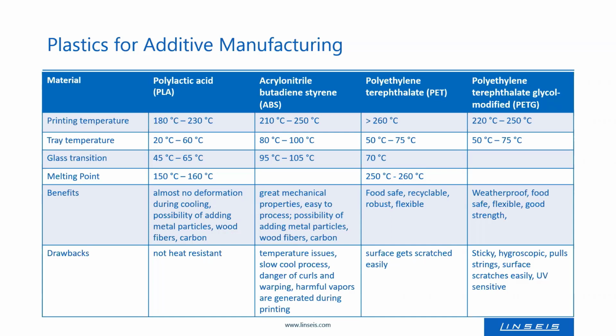The next two large groups of used filaments are PET or PET mixed with glycol. So by that, one can achieve some different properties. So for PET, for example, the printing temperature is above 260 degrees Celsius. Thus, a heated tray is also needed. And the advantage here, it is food safe, one can recycle it, it's robust and flexible. So PET, you all know from the water bottles, for example. And PET is also a good alternative for ABS, since during printing, no harmful vapors are generated.